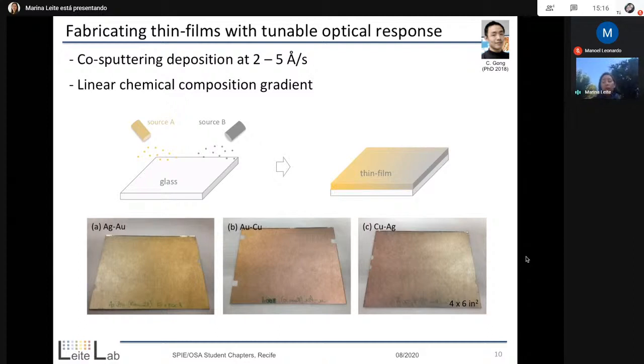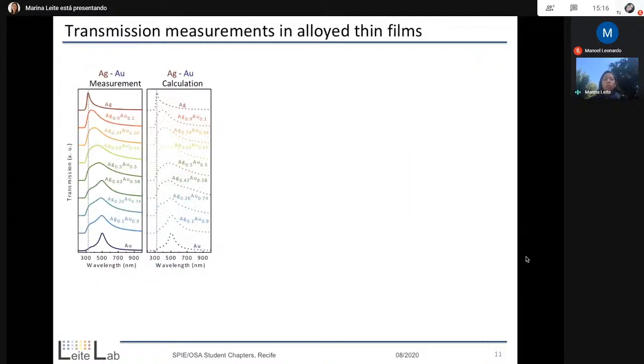So once we checked the chemical composition gradient in the samples, the first thing you do if you're working with optical materials is light transmission measurements, okay. In this case, in the visible range, because that's what we're interested in. And what we see here on the left, the measurements for silver and gold, and calculations for the same binary mixture, is that from pure gold to pure silver, we shifted the peak in transmission, very expected due to the surface plasmon propagation. We have a contribution of both metals here, right?